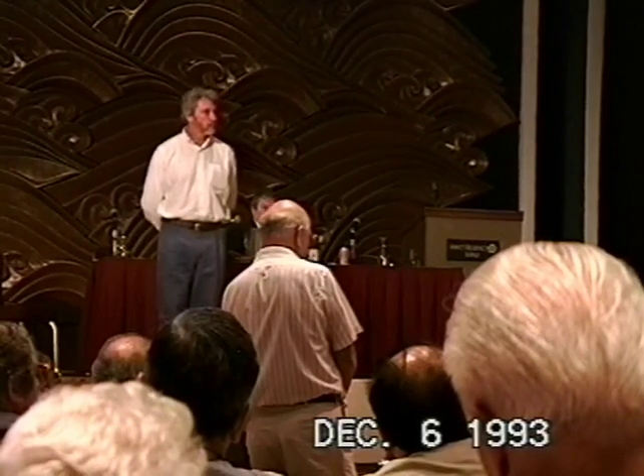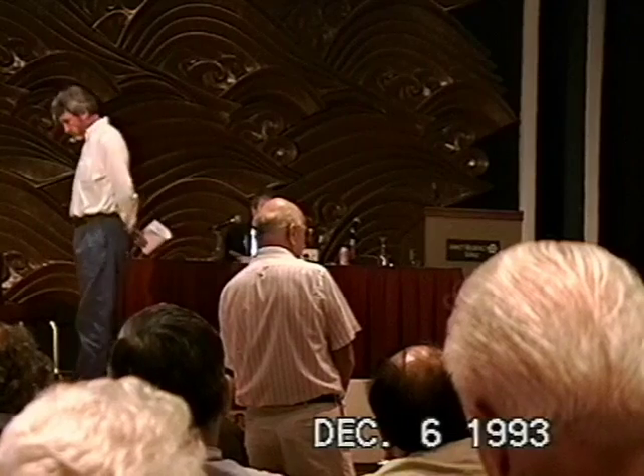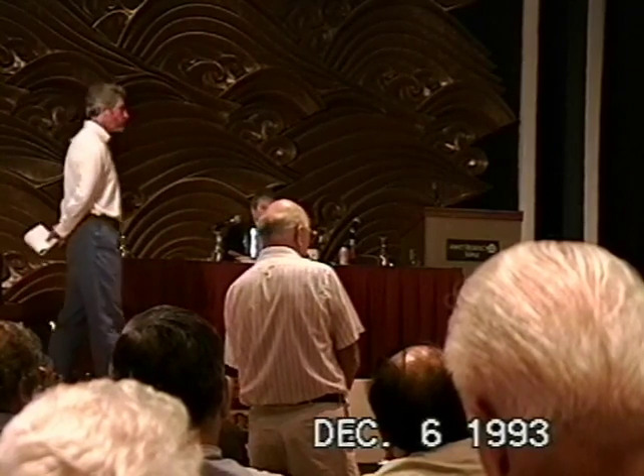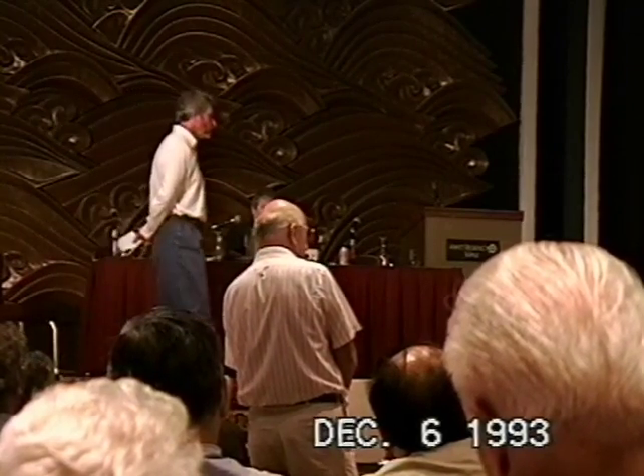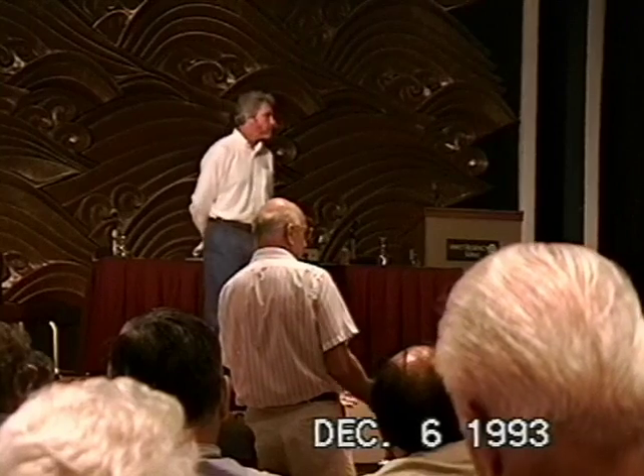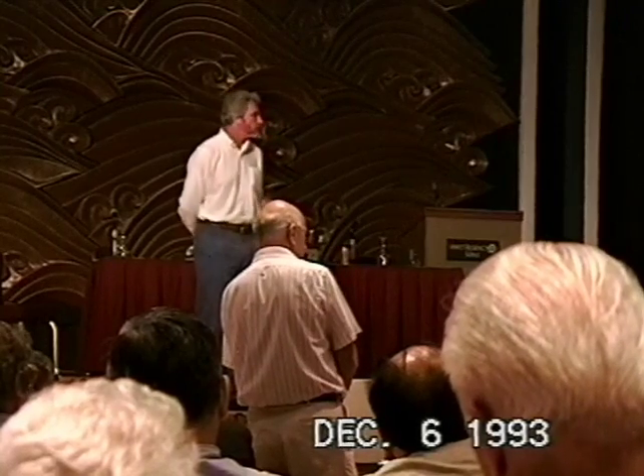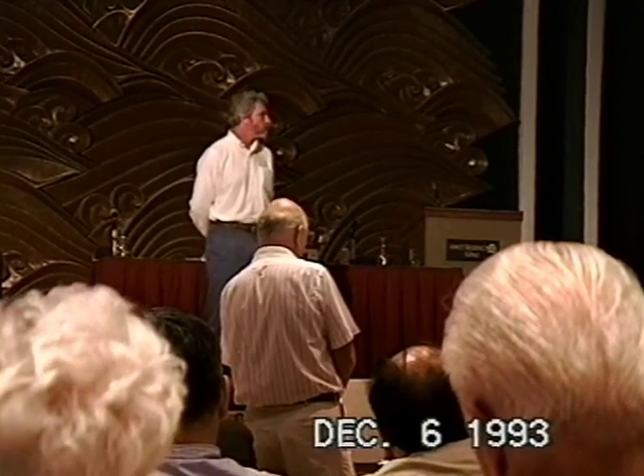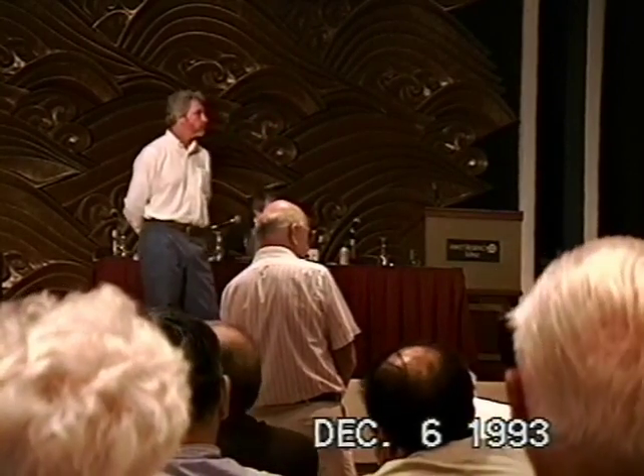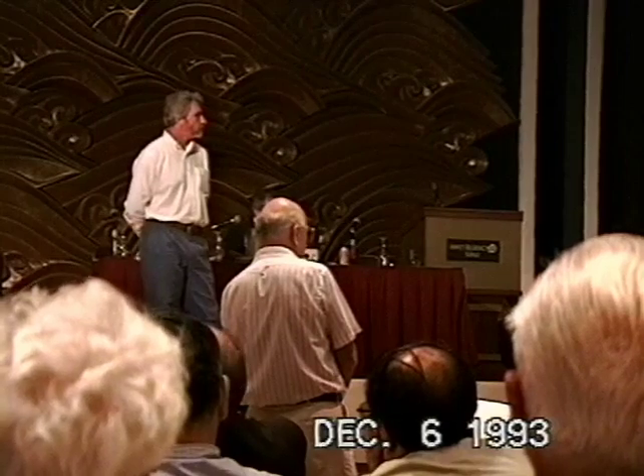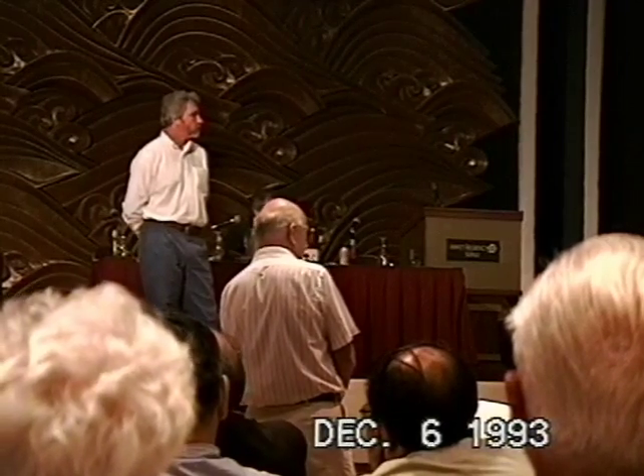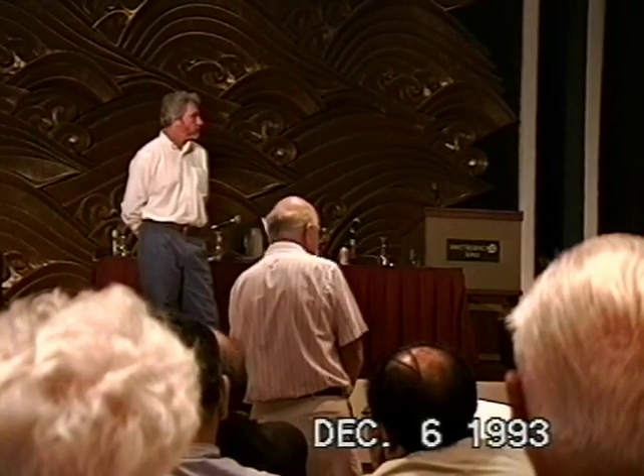The issue, of course, is that there are always surface films that build up after some time, and that these add to the overvoltage. And these surface films can be quite significant. And we've observed at times when events have occurred that these surface films have been flushed off from the overvoltage, or at least the cell voltage changes significantly. So what we need is a way, obviously, to measure the true overvoltage of the electrode, a way to distinguish between the solution resistance and then the surface film resistance. Well, about the thiourea, I agree with your comments.